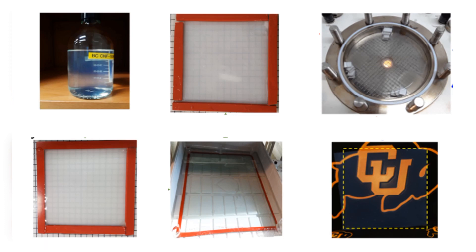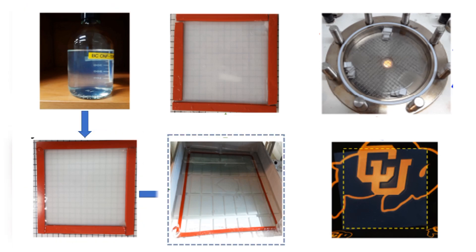To solve this problem, Ivan Smalyukh and his colleagues at the University of Colorado soaked nanofibers of cellulose extracted from wood in water. The wood nanofibers were then removed and dunked in an ethanol solution. Once saturated, the nanofibers were heated in a pressurized oven to force the ethanol pockets to be replaced with air. Next, the transparent nanofibers were coated with a water-repellent silicon compound to prevent condensation when situated between panes of glass.